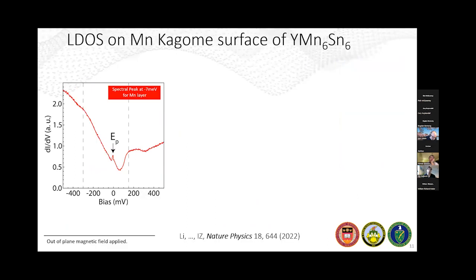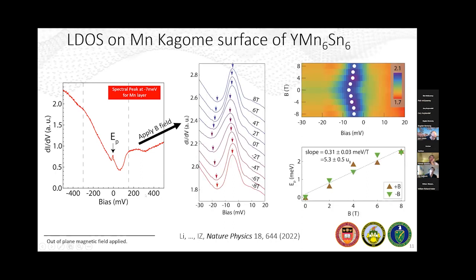So the first thing we do when we approach a new sample is measure the dI/dV spectrum. This is an average dI/dV spectrum on this manganese termination. The x-axis is bias or energy, and the y-axis is essentially density of states. What I want you to focus on in this system is this little peak near the Fermi energy. We want to investigate the nature of this peak, so we apply a magnetic field. The magnetic field is applied out of plane.